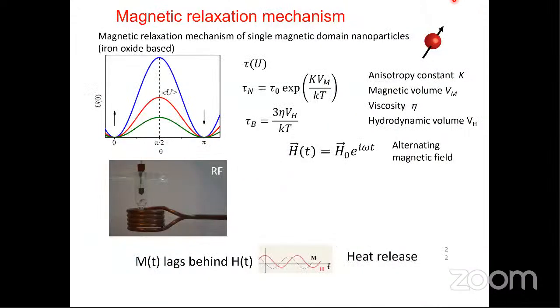This procedure relies on magnetic relaxation mechanisms. We have our single magnetic domain nanoparticle, and this nanoparticle has to overcome an energy barrier. It can be done using two mechanisms. One is the Néel mechanism, where the nanoparticle is fixed in space and the magnetic moment switches from one direction to the other, and the other is the Brown mechanism, where the particle itself, with the magnetic moment, rotates in space. In any case, the magnetization lags behind the field, and due to this lag, there is a heat release.